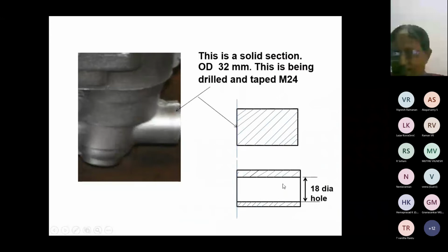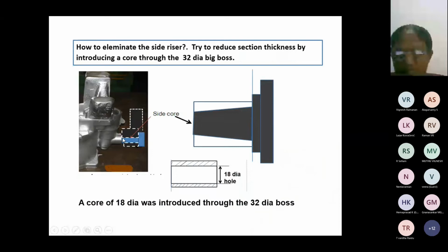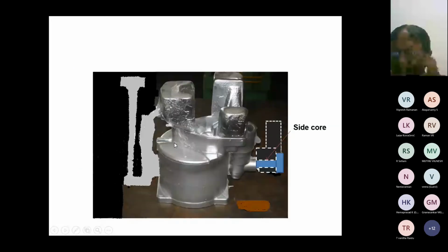See, we have provided a core hole of 18 mm diameter through this 32 mm OD. This is the die. This is the core. We try to put it from this one by modifying the die. This is the core. Each 18 mm in diameter to a length of about 40 mm is quite a good material removal. And we tried to pour some castings.